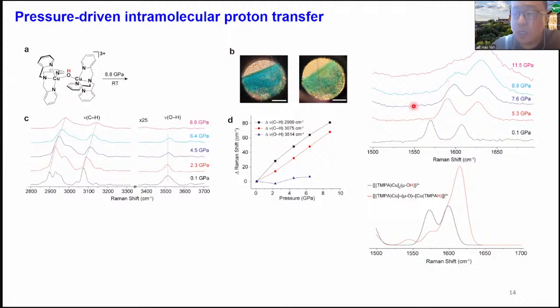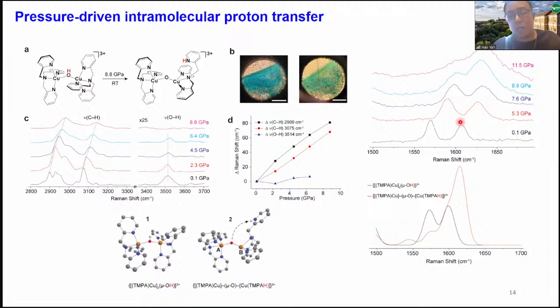We can also see that the breathing mode of the pyridyl rings changes profile and going towards a pyridinium, or a pyridyl plus a proton. So combining these evidences, we think that what happens is that the pressure drives an intramolecular single proton transfer. So the hydrogen on the hydroxyl hops off and goes to one of the pyridyl arms of the TMPA. That arm then dissociates from the copper, generating a compound like this.